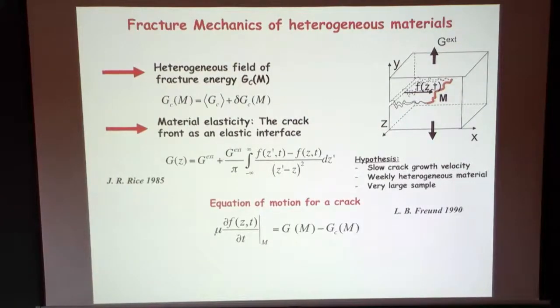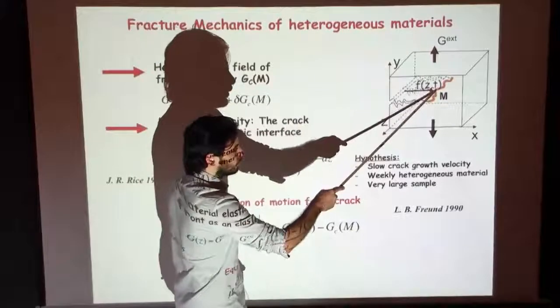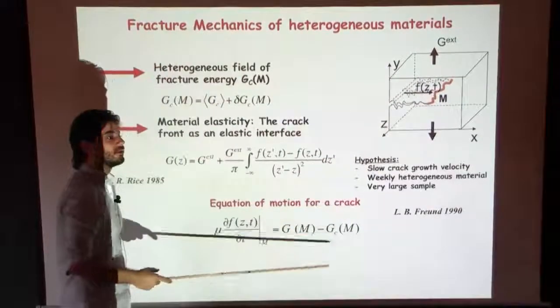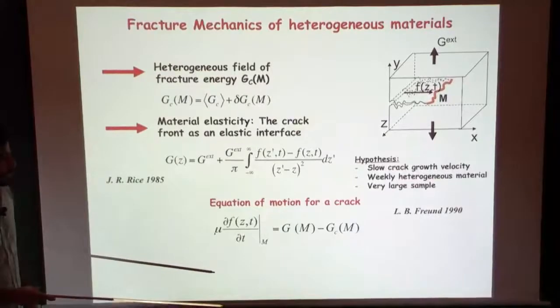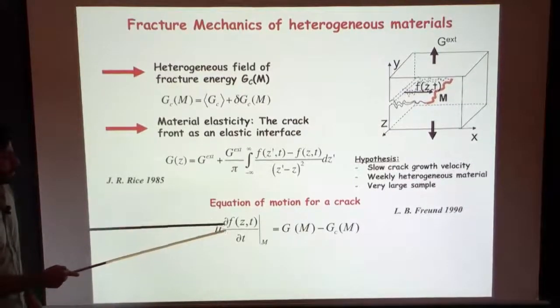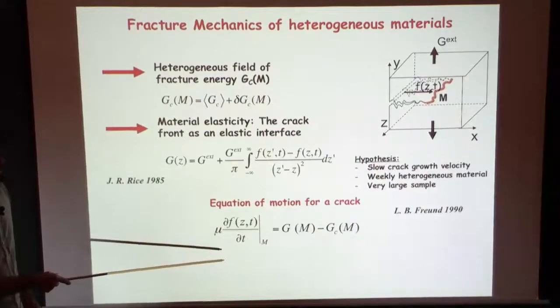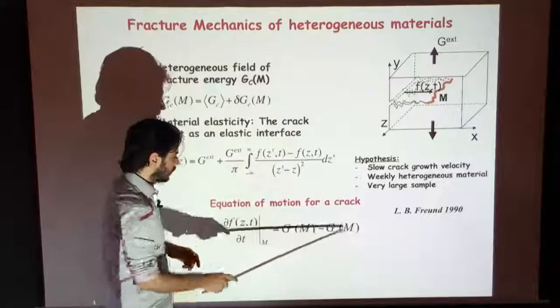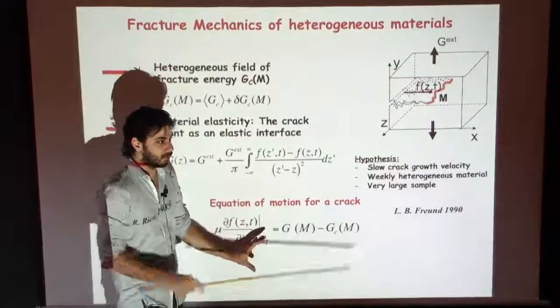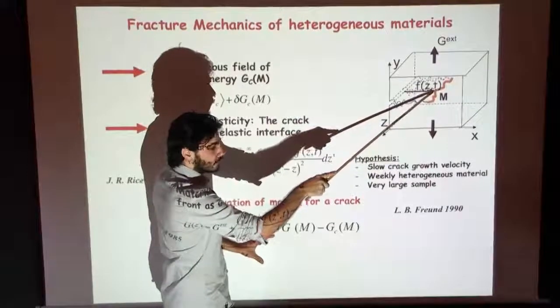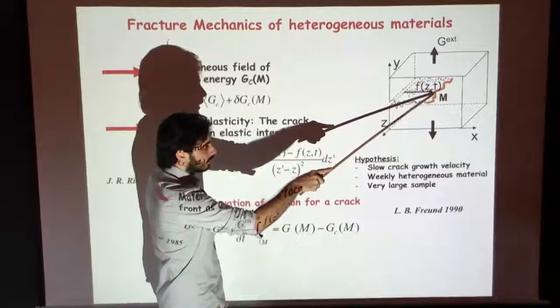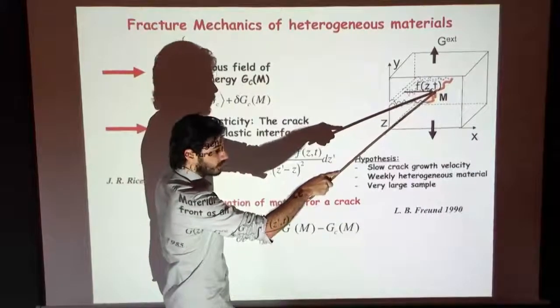Just a naive question. I don't really understand. What is M? It's a point on the front. Why isn't it just given by f of z of t? So f of z comma t completely specifies the location of the crack. I want to insist that it's a local propagation law that you apply at every point along your front. Let's consider this point along the crack, along this orange line, yes. At this specific point, I can predict the local velocity of the crack. It is going to move forward if G is larger than GC.